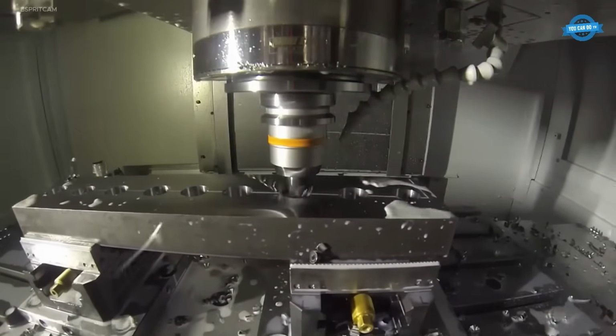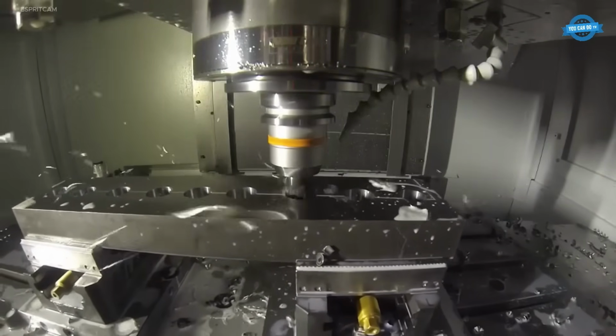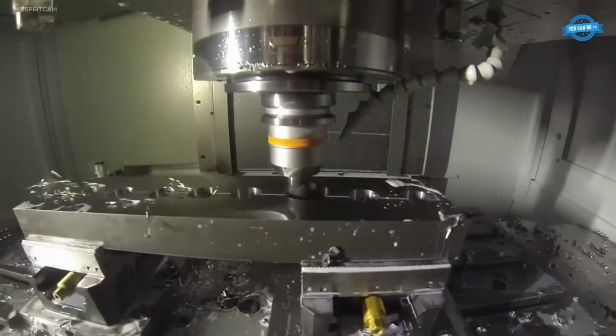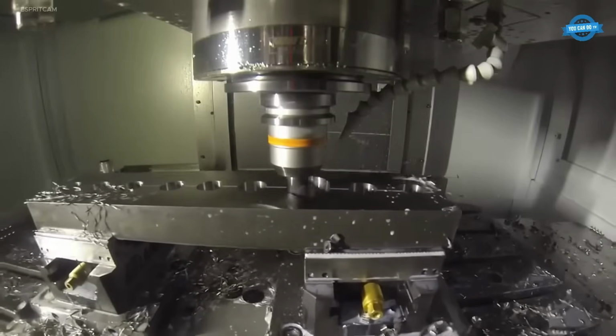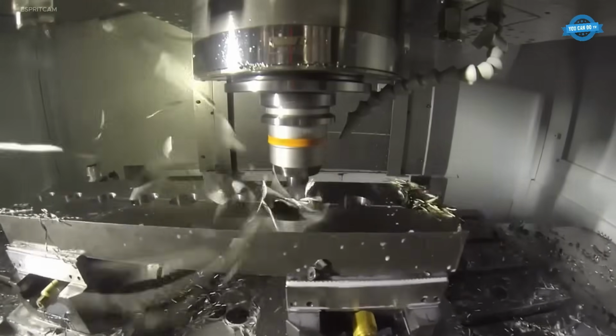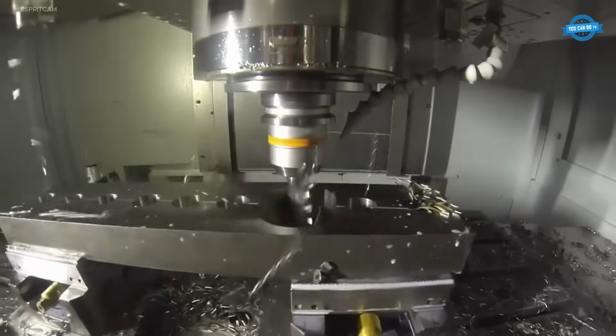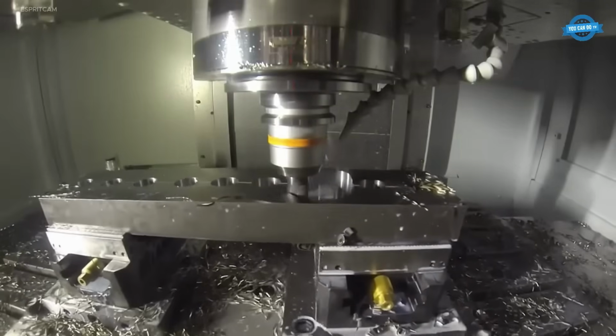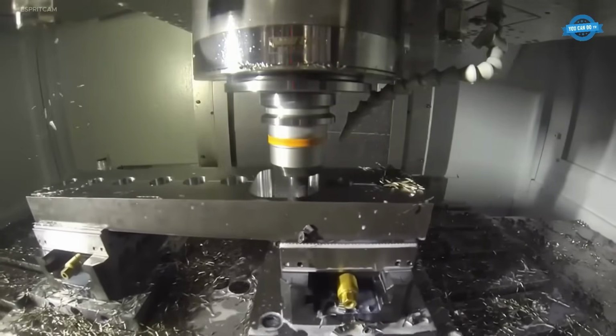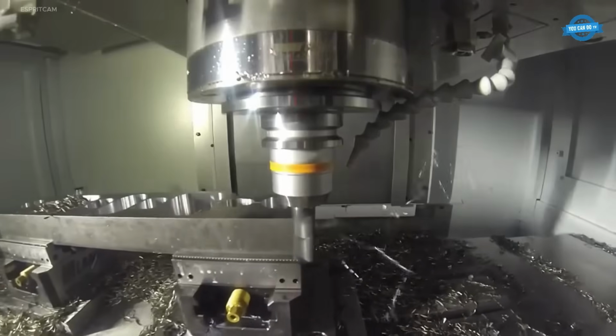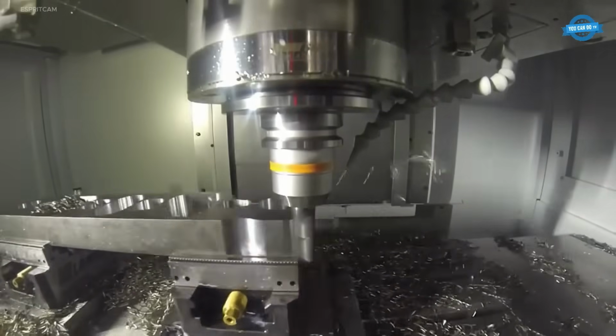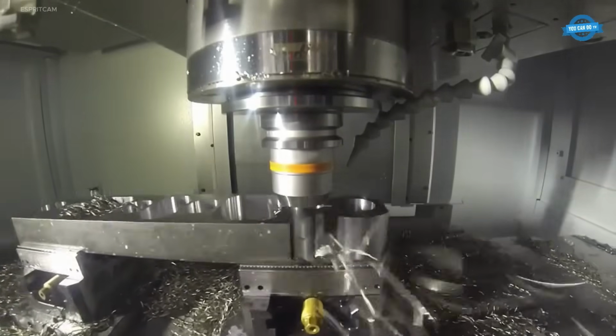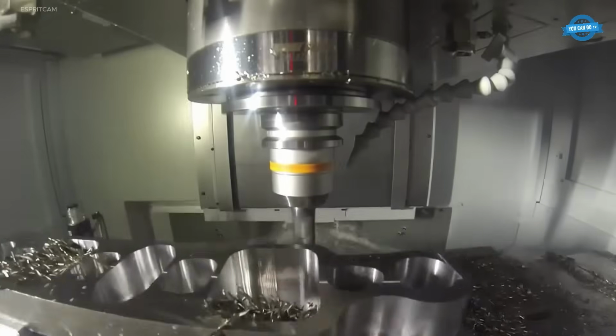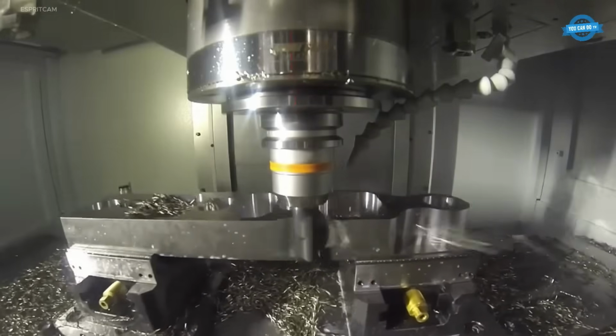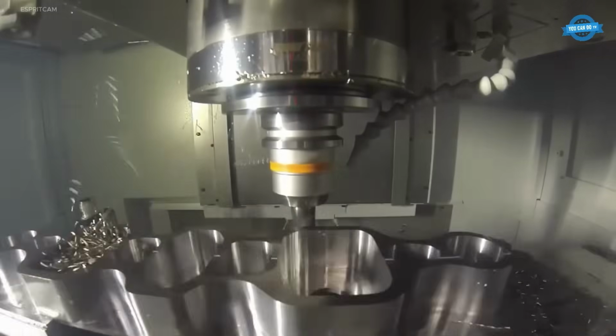Using profit milling on a Mori Seiki NVX 5080 slashes cycle time from 52 minutes to 14 minutes, while boosting tool life over 500%. A 20mm Paul Horn end mill roughs CK45 aerospace stock at 6,000 mm/min, 0.38 mm fz, 5,000 revolutions per minute. With a 25% engagement angle and 35mm axial depth, the strategy maintains constant chip load, minimizes heat, and maximizes spindle efficiency.